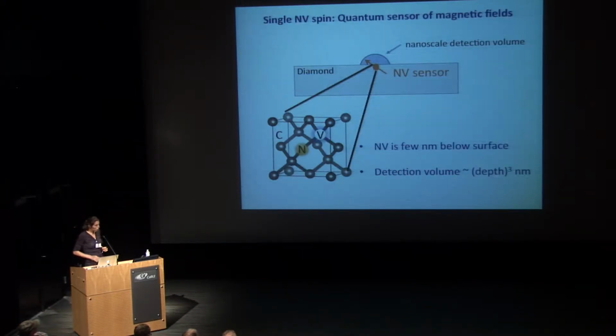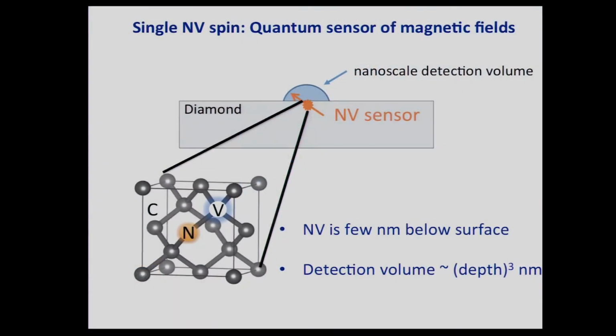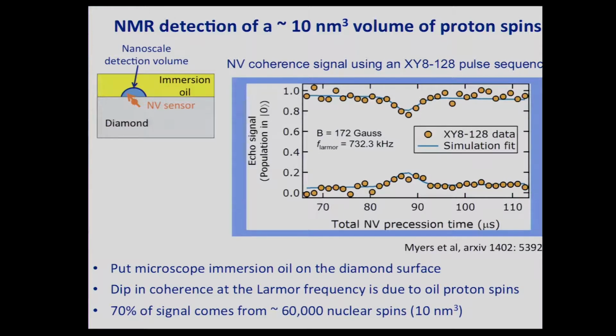Okay, so we've used the magnetic sensitivity of the NV center to do nanoscale magnetic resonance. What we've done is we've taken a bulk diamond sample with NV centers a few nanometers below the surface, which we can controllably place there. If an NV center is only a few nanometers below the surface, its detection volume is on the order of the depth cubed. So in this case, we looked at an NV center that was 10 nanometers below the surface. We put a drop of immersion oil on the surface.